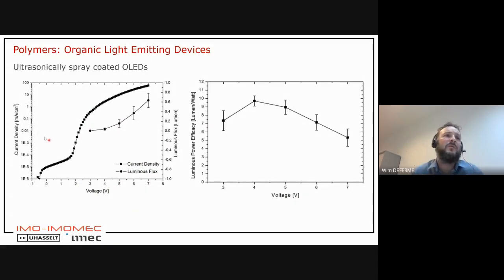And then finally, we looked, of course, at the current density and the luminous power efficacy of these devices. And we see nice results, comparable results to spin coating on the current density. The luminous flux gave also more or less the same results as we have with spin coating. And we have a somewhat lower luminous power efficacy than with spin coating, where for spin coating we could go to, let's say, 15 to 20 lumen per watt for this specific stack and this specific material. But we concluded that this is the final design, or the final layer that we printed.